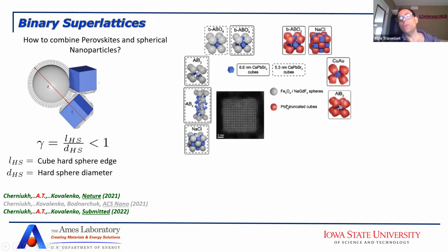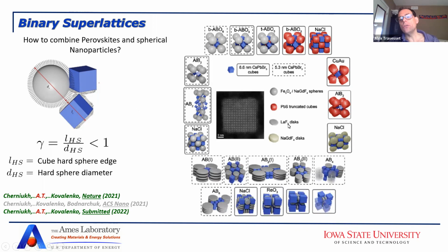You can also play with truncated cubes. And then when you combine the cubes with truncated cubes, you get these other phases: b-ABO3, sodium chloride, AuCu, AlB2. You can also even make ternary phases where you combine spheres, cubes, and truncated cubes. Then the group of Maxim Kovalenko is also able to make sodium gadolinium fluoride disks and lanthanum fluoride (LaF3) disks, and then you get a whole bunch of new discotic and also cubic phases like this. So this is actually the current state of the phase diagram that we have for combining things with different shapes: there are cubes, there are disks, truncated cubes, and spheres. So this is the system. Most of these are binary, but this one happens to be ternary.